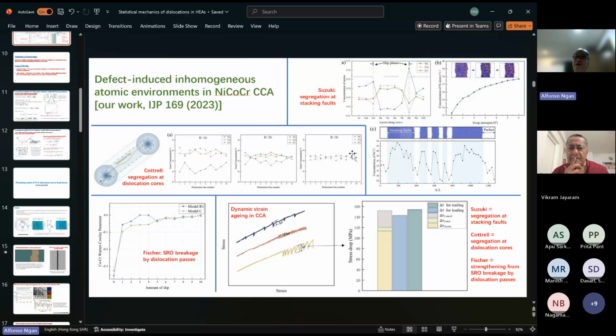So for BCC, obviously we will not be talking about the stacking fault, but we may be talking about the APB arising from ordering. But even in a BCC material, the actual slip path leads to some initial displacement, which is a generalized stacking fault immediately followed by something else. So it's not obvious that the treatment needs to be any different. Even if the final Burgers vector is 1/2 <111>, it's made up of individual slip movements. Am I right there? Yes. So there is some stacking fault involved, or there's a combination of displacements involved in arriving at the final Burgers vector.